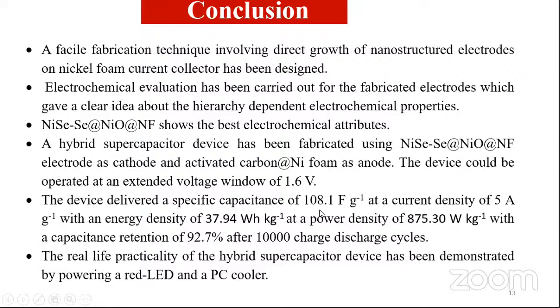The device delivered specific capacitance of 108.1 F per gram at 5 ampere per gram with energy density of 37.94 watt hour per kg at a power density of 875.30 watt per kg, with a capacitance retention of 92.7% after 10,000 charge discharge cycles. The real life practicality was demonstrated using a red LED and a PC cooler fan.